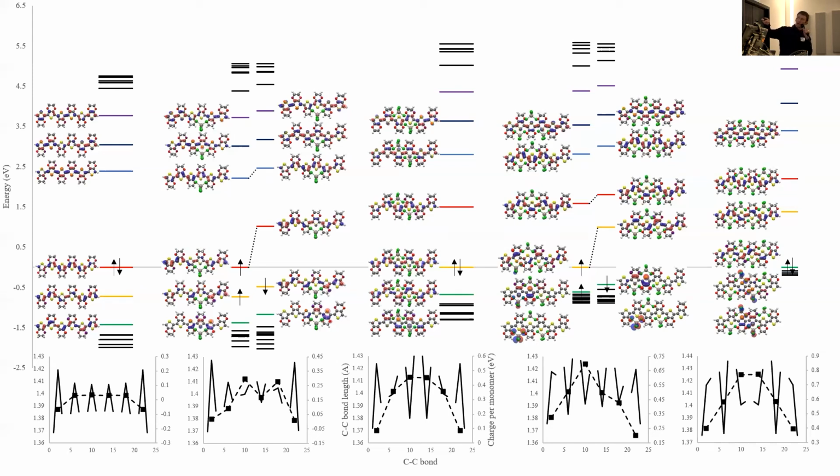Now, when the original researchers first started looking at the spectroscopy and doing this experimentally, they noticed that when you took out 1 electron, you ended up with what looked like an extra state here and very clearly an extra state here. And then if you took out an extra electron, the band structure changed again, and there was an extra state here. Now they theorized that as you bring in an anion, you introduced a bonding and an anti-bonding state that would appear in the gap.